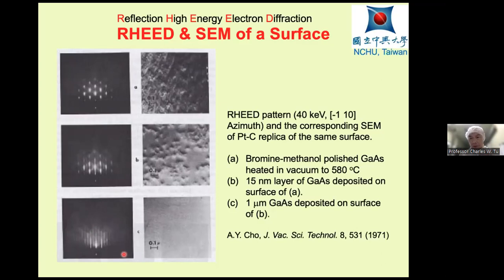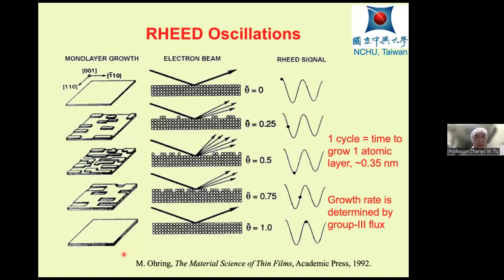First, the oxide layer is removed, because any time we expose a material to air, we have a thin layer, about 15 angstroms, of oxide. So we have to dissolve it to expose the underlying single crystalline structure. And after we grow, let's say, 1 micron of gallium arsenide, the surface is atomically smooth.